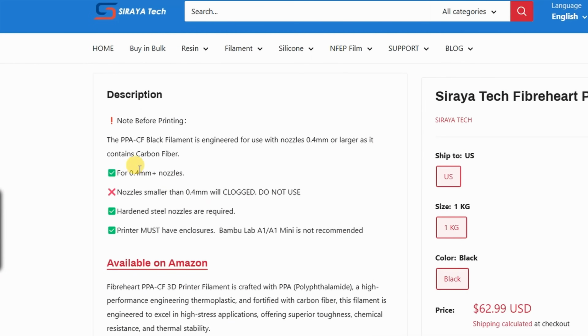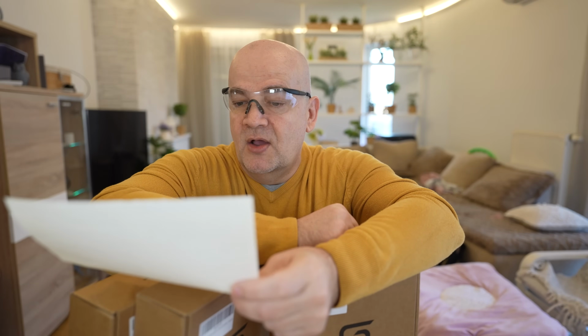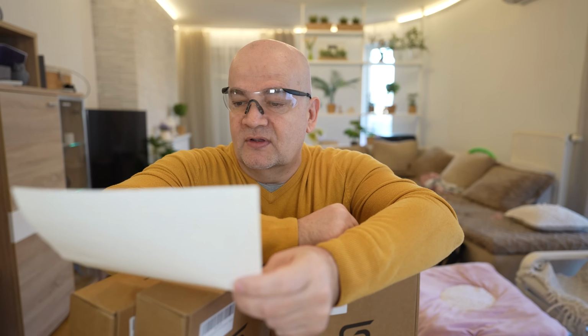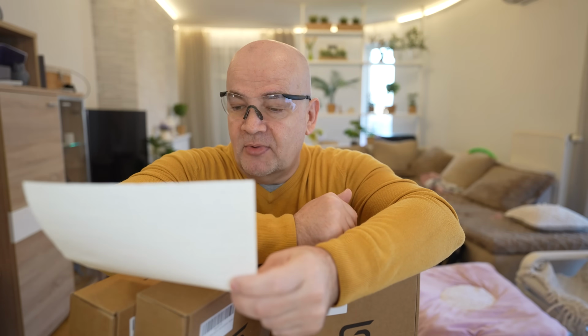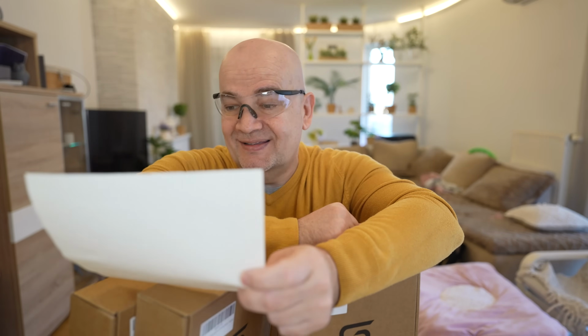About print settings, we need a 0.4mm nozzle or bigger, and of course because of the carbon fibers we need a hardened steel nozzle or some similar hard material, and of course we need an enclosure too. About bed temperature, 80 degrees Celsius in all three cases, PEI with some glue stick on it and it will be fine. For the non-carbon fiber version, the nozzle temperature between 260 and 280 degrees Celsius. For the two carbon fiber versions, the nozzle temperature between 300 and 320 degrees Celsius.